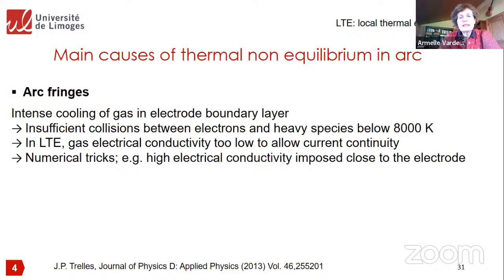Why is there thermal non-equilibrium in the arc? First, there is some in the arc fringe. When the arc comes close to the electrode, for example, close to the anode, which is very intensively water-cooled, the arc will also be intensively cooled down. Because of that, you will not have enough collision between the hot electron and the heavy species when it goes below 8,000 degrees.